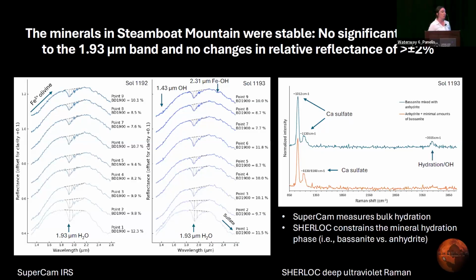So we didn't really see any changes greater than 2% that are visually apparent in the 1.9 micron region here, that we can actually see with the eyes, but then the calculations do indicate that there isn't much of a difference. But SuperCam measures bulk hydration. So Sherlock is particularly important for constraining the hydration phase, which you can see in the Sherlock DUV Raman there, where we're seeing an actual mixture of bassanite and anhydrite, which is actually inconsistent within the Steamboat Mountain abrasion patch, where we see areas that are more hydrated than others.